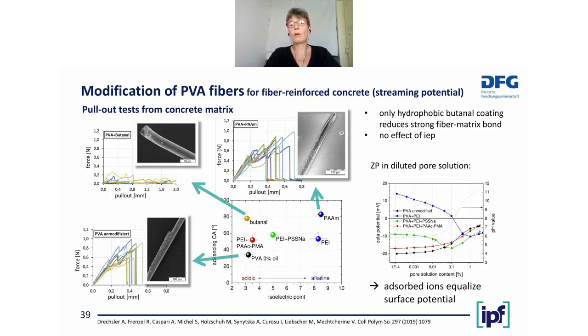We wondered a little bit why the polyelectrolytes did not affect the interaction very much, but then we put the fibers in diluted pore solution. Pore solution is the liquid you get if you filter fresh cement. So it's a solution that contains very many ions of different kinds. And if you put the fibers into this diluted pore solution, you see that no matter which Zeta potential the fibers have at the start, already in 1% pore solution, the surface charge is the same for all fibers. So probably that's the reason why this effect was not very big.